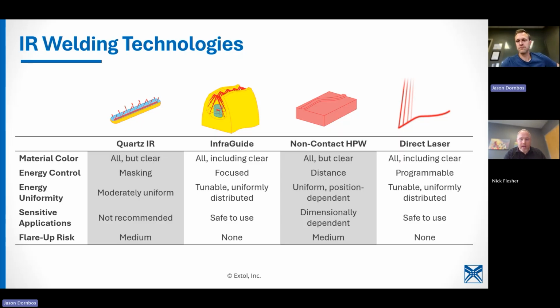Usually we want temperatures above 900 degrees Fahrenheit. And then direct laser, you saw a video of. I don't think we had a non-contact hot plate welding video, but that looks like hot plate, and you just park out. Get real close. The goal is like under 60 thousandths of an inch. If you go over 60 thousandths of an inch, you get an exponential increase in time. So we do have customers that struggle. They can then, from a dimensional standpoint, get on the upper side of that.